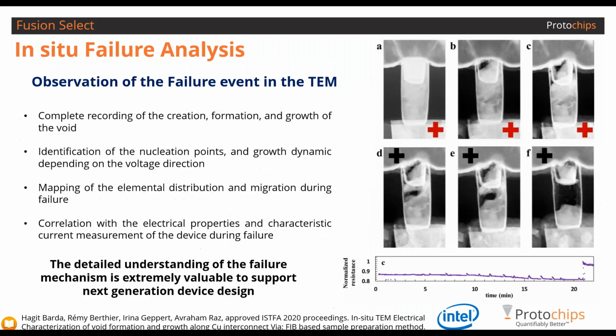So we applied the method that we just described, and we were very successful and have been able to observe the in situ failure event, the entire dynamic of this event. We recorded the movie of how a void, a hole inside the via, was nucleating, growing and changing its structure and morphology; how, thanks to EDS analysis, different chemical elements were migrating and modifying the property of the structure; how the polarity that you apply to this wire in order to run a higher current changes the behavior of the failing mechanism; and we linked all of those structural and chemical information to the electrical property of the wire and saw how it was disconnecting.